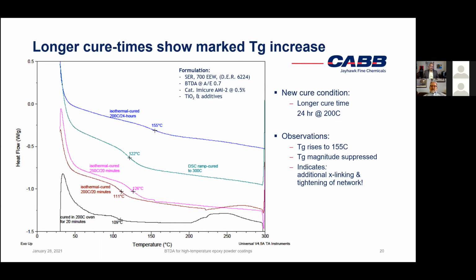Anyway, yeah, and that's a more eloquent way of saying what I did. What we think was happening is that there's certainly chemical reactions taking place, some bonds are taking place, but perhaps some bonds are getting further strengthened. Some cross-links are getting more thermodynamically optimized in order to boost the TG further and further and suppressing the transition itself. But overall, the magnitude of those reactions from a thermal energy release is very hard to predict, at least using these experiments.